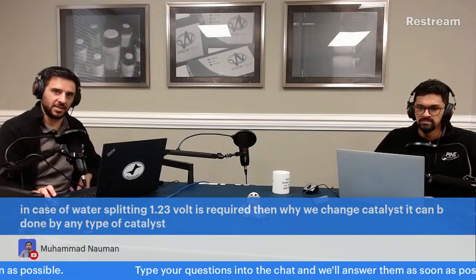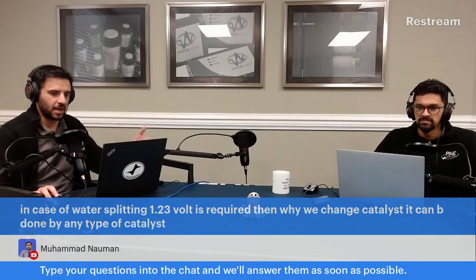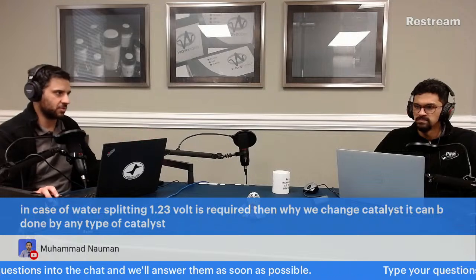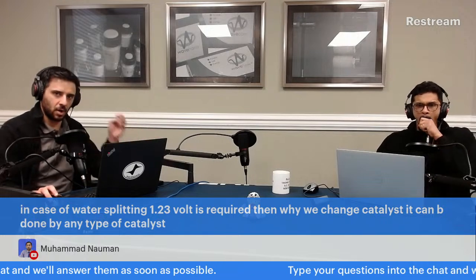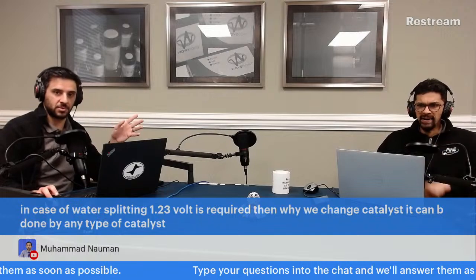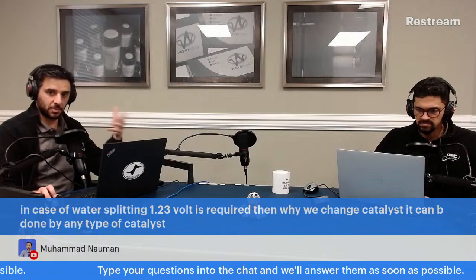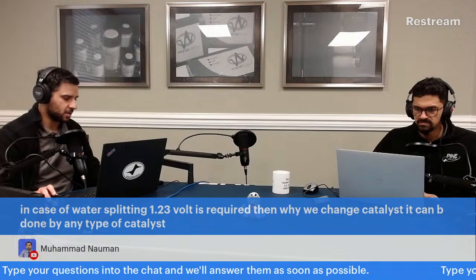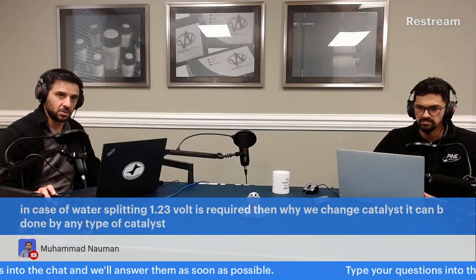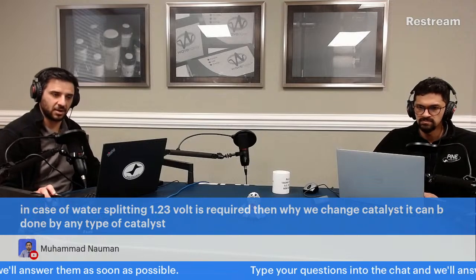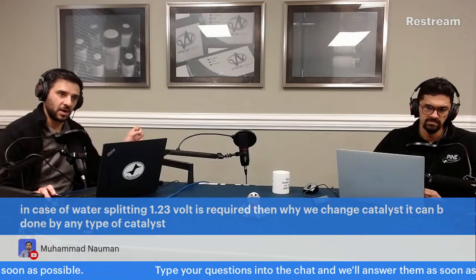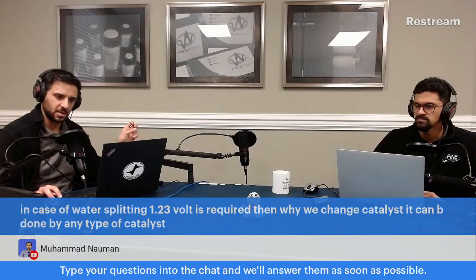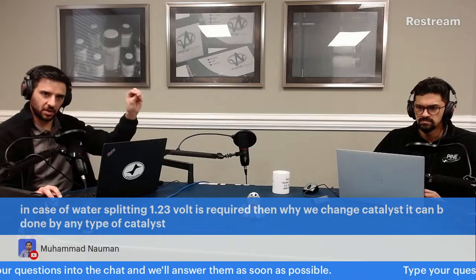It's a substrate, right? It doesn't get in the way. If you put platinum on carbon, or you put palladium, or you put ruthenium, that does a good job at ORR, right? And you don't want your substrate getting in the way, which is the point. It doesn't really interfere or contribute. And if it does contribute, it's not much. Comparatively, even when you compare the bit of oxygen that glassy carbon reduces, it's like 1% of the current that platinum will do.